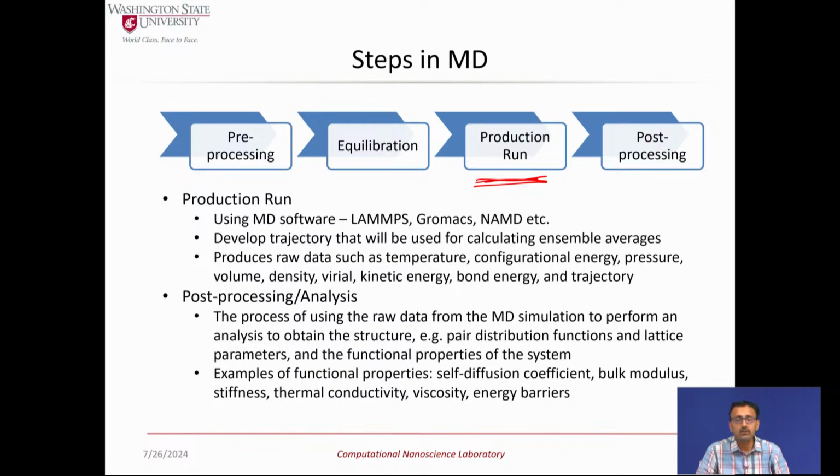Another example of a non-equilibrium calculation is, let's say you want to calculate the thermal conductivity of a crystal, right? You can impose a temperature gradient and look at the response to that temperature gradient, from which there is either a Green-Kubo or Müller-Plathe formulation to estimate the thermal conductivity of that material. Obviously, it's non-equilibrium because there is a gradient, in this case a temperature gradient.